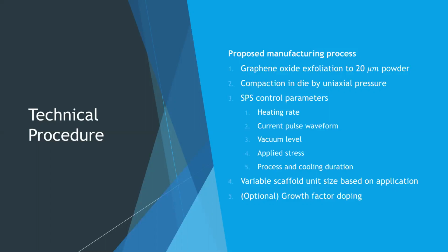One possible option for a final step is growth factor doping. In order to increase its effectiveness in grafting, testing shows that low oxygen content graphene doped with mesenchymal stem cells resulted in significantly increased bone formation and mineralization.